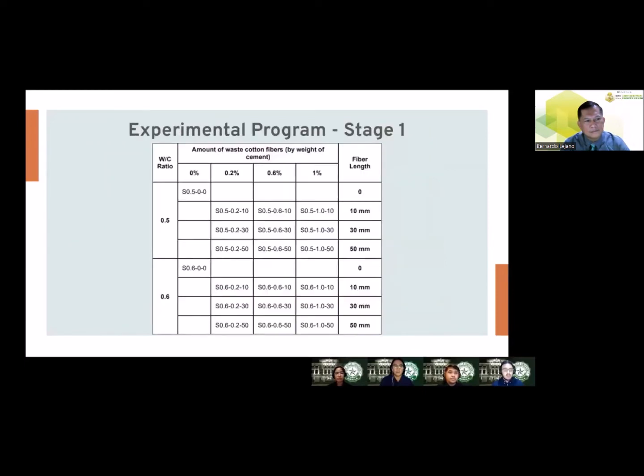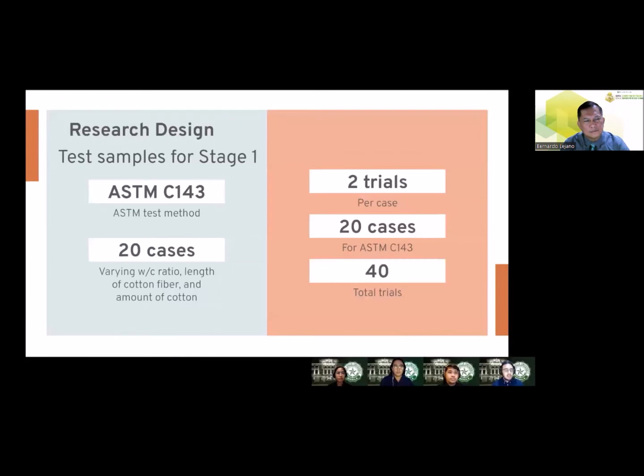Now, for stage one, this involves the workability test. As shown in the table, the samples are categorized by the water to cement ratio, amount of cotton, and cotton length. For stage one, there are 20 cases to be tested as seen in the previous table. For each case, 2 trials were conducted, which overall resulted in 40 total trials for stage one. Stage one determines the water to cement ratio to be used for stage two.